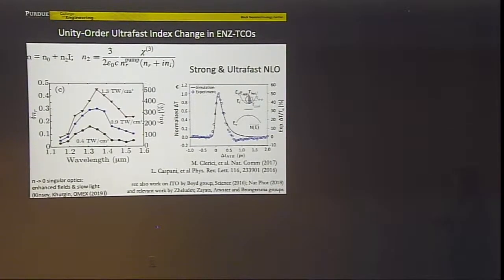And so what we obtained is a nonlinear term, in this case, 5 times higher than the linear term. Actually, in later experiments, we showed 100 times higher than the linear term. This is hard to imagine. I mean, you never have it with conventional materials. Nonlinear terms are not just, let's say, significant. We say significant when it's 0.1%. It's actually 100 times larger than the linear one. And I should admit there is no theory for this. It requires development of an entirely new theory.